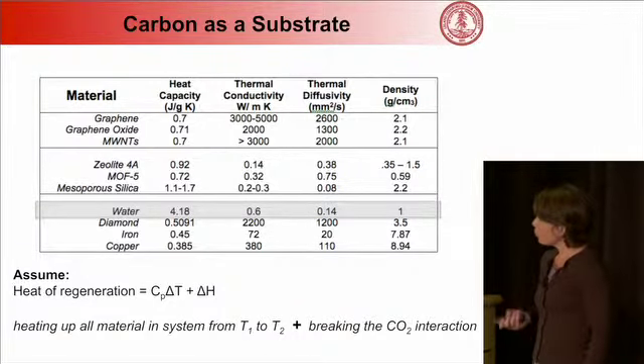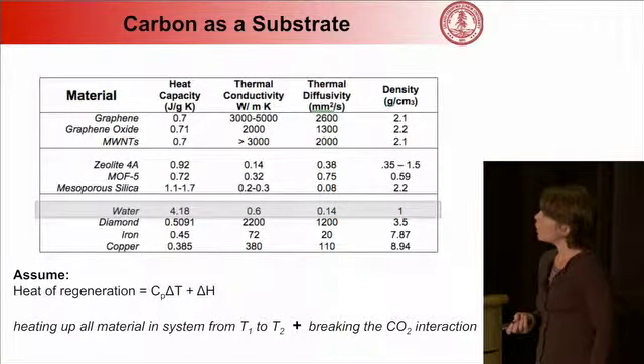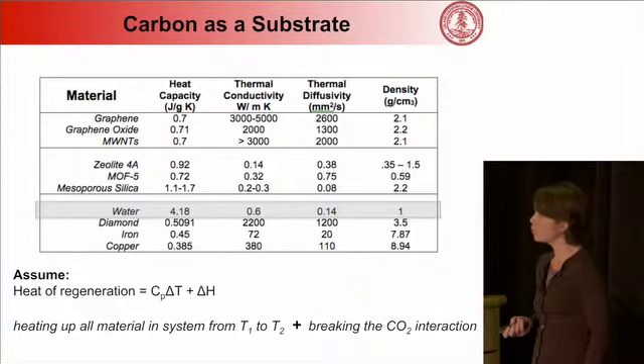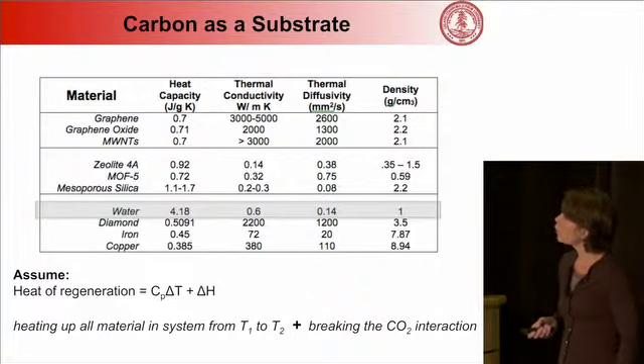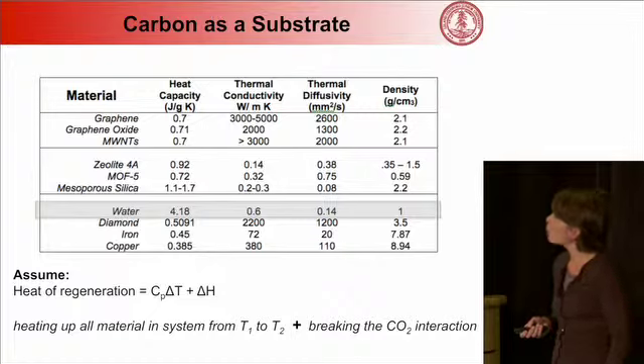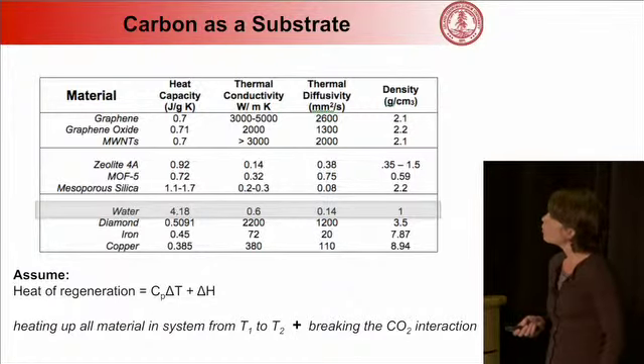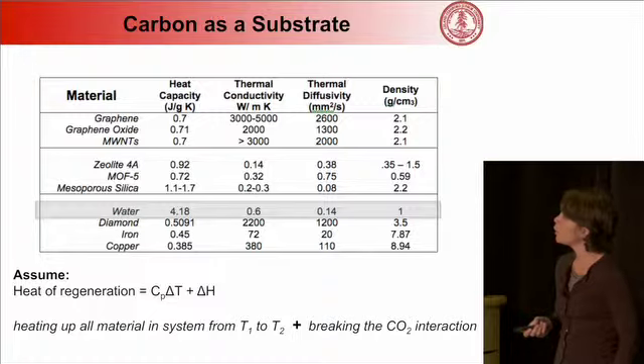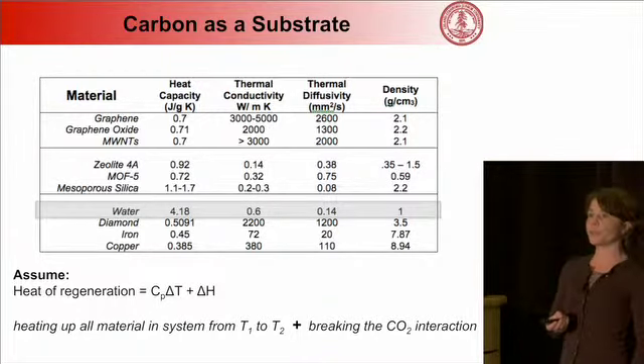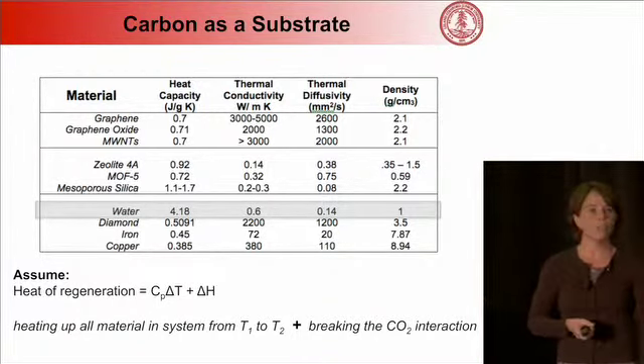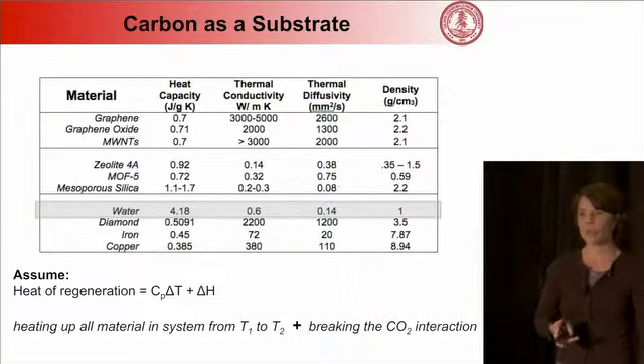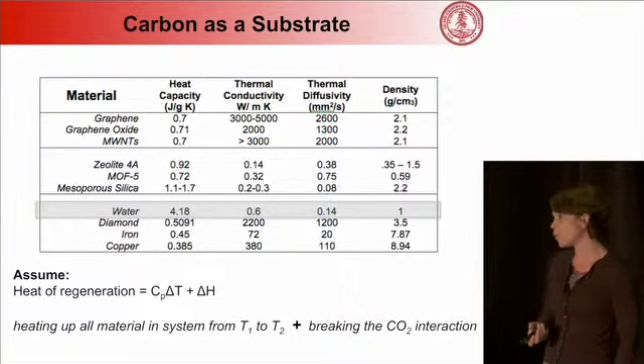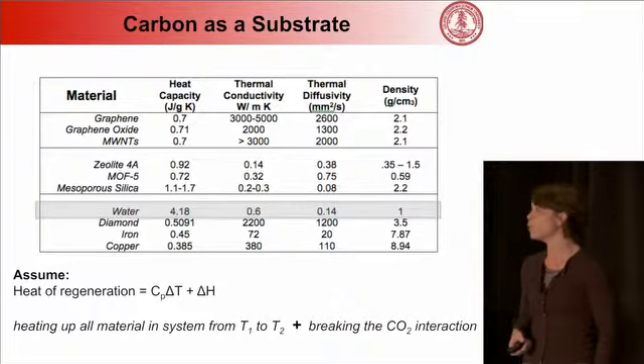So the substrate that we chose was carbon-based. And the reason why we thought about carbon is because of the heat transfer properties. For instance, if we look at this table, we can see at the top you have graphene, graphene oxide, and multi-walled nanotubes. And all of these carbon materials have relatively low heat capacity, say, compared to water. So if you were to compare this to a traditional amine scrubbing process where it's an aqueous phase and you've got about 70% of that as water, which drives a lot of the regeneration costs of that process.